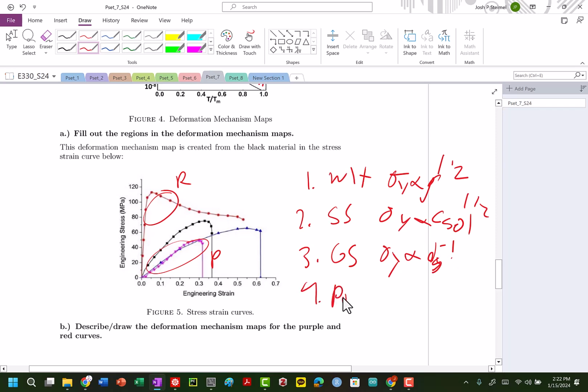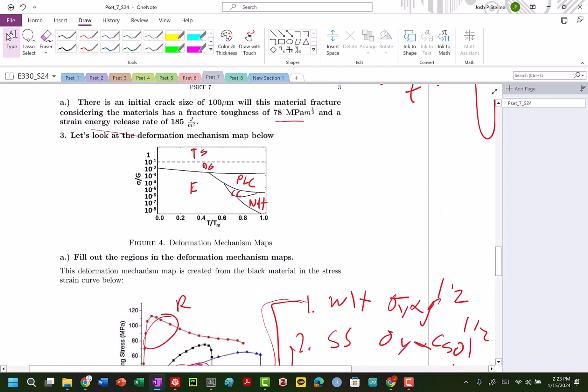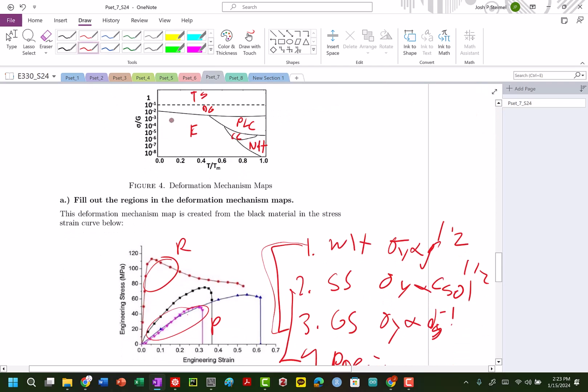These two, 1 and 3, are interrelated, so if I do one of these operations, I do the other. Typically, if I'm taking a material and producing different stress strain curves using method 1 and method 3, my Young's modulus must be the same. So I know in this particular problem, from what we talked about in class, it is probably 2 and 4 that are occurring. And that's not really going to change anything except that if I'm looking at my purple curve, my yield strength is lower than this black curve. So this line will decrease here.